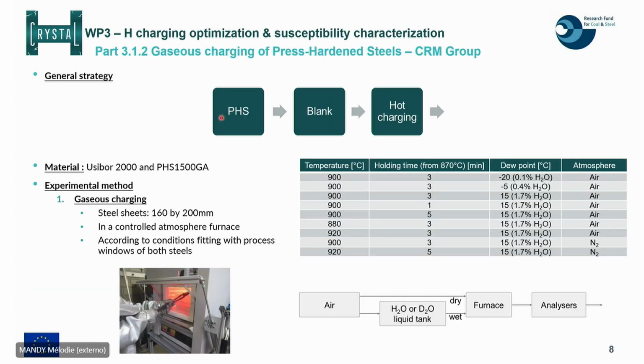So now for the press hardened steel, we are on the other topic. For that part, the strategy that was followed was to charge them with what we call hot charging. So it's actually a gaseous charging in a furnace. This was performed for both press hardened steels, Usibor 2000 and PHS 1500. It has to be mentioned that Usibor 2000 is a material that was coated with an aluminum and silicon coating, while PHS 1500 was actually with a zinc coating. It was actually a GA, so a galvanized coating.